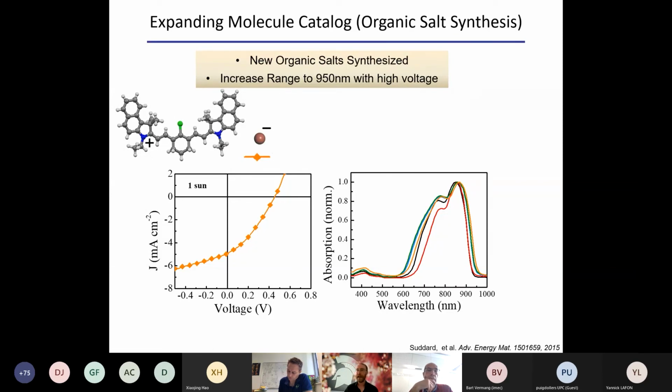And it's based on a cyanine salt. So this is a polymethine cyanine salt where we have a cation and a counterion. And so this is like sodium chloride, but now we can make the cation and the counterion both organic. And this has been used historically in like CD-R recording media. And a number of folks have been playing with variations of this, but we picked this particular one because the band gap was deep into the near infrared with very good wavelength selectivity.